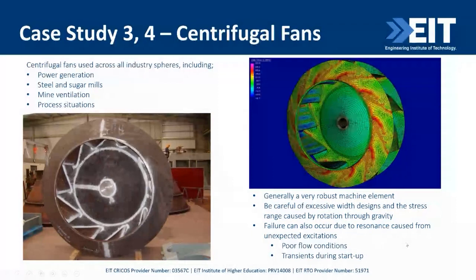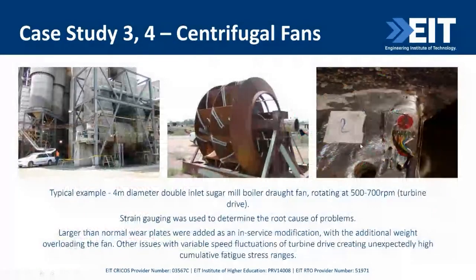Be careful of rotation through gravity and poor startup flow, as well as losing control of wear plates. This is a large double inlet sugar mill fan, which unfortunately lost control of wear plate masses, and also was not controlling it well on the turbine drive. So these things start on a pony drive and switch to a steam turbine, and they had 500 to 700 RPM turbine speed variations. And if you look at that, 500 to 700, that's a fatigue cycle itself. It's causing an up and down of a fatigue cycle itself. And if you keep on doing that, even twice every minute, you're quickly going to rack up unacceptable cycles.